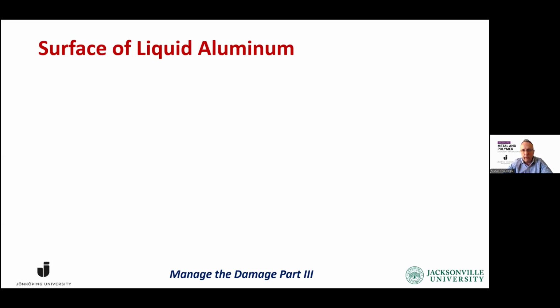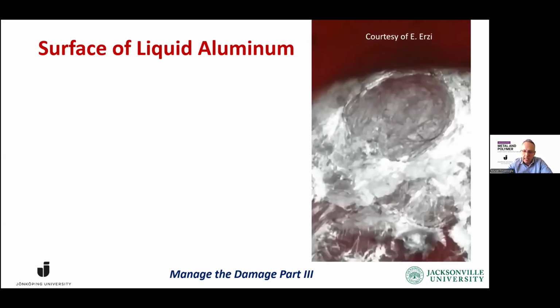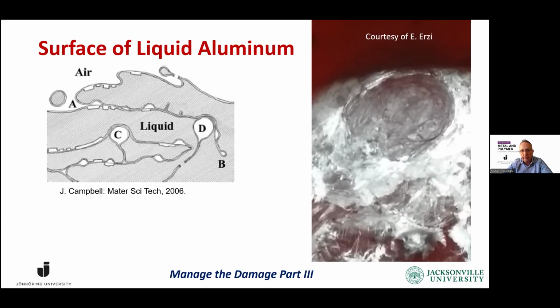Now, the surface of liquid aluminum, on the other hand, is not covered by liquid aluminum. It's covered by a solid ceramic. And as long as this solid ceramic remains on the surface, it's harmless. But because we disrupt the surface so many times, that surface ceramic is incorporated or entrained into the bulk of the liquid, creating a non-bonded surface that we call a bifilm, because there are two films on each side. And that is the start of the damage.